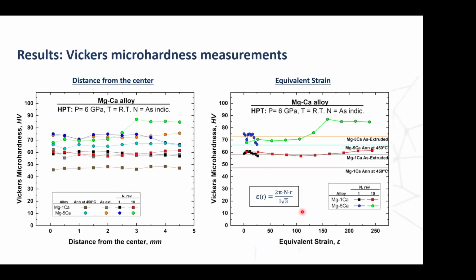The hardness is shown here. As I said before, in this case, the increase in hardness is not so significant, but of course, with the number of turns and with the amount of calcium, we will get harder material or strengthening because of dispersion and dissolution of these magnesium two calcium particles, and that certainly will increase the strain, especially at the periphery of the discs. We did see that the strength starts increasing as well.